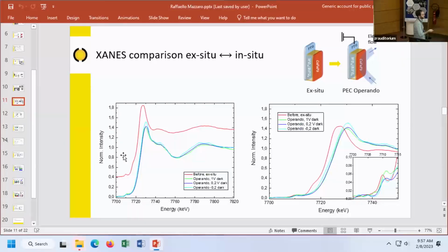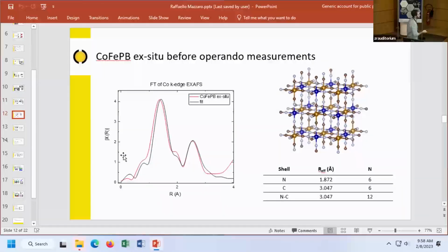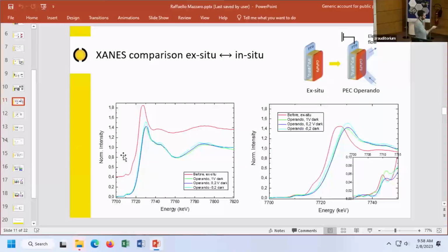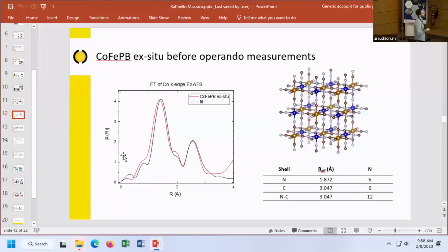So we have both the change in the white line and the edge position, and also the pre-edge peaks. So that is pointing out that we have already, just by putting the co-catalyst in contact with the electrolyte, a swift variation of the local structure of our catalyst. And also you can see that we have some much smaller, but non-negligible variation of the XANES spectrum for different potentials. And these are all in dark for now. So we'll see later what light does in this kind of thing.